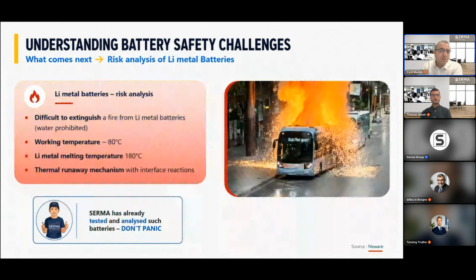The same also happens for the next generation. So here the lithium metal battery first. Here there is some fire. When it takes fire, you see that the fire is not exactly the same. Here it's not the electrolytes that burn. It's mostly, and you see some particles in this picture here, lithium metal that is melted. The disadvantage in the risk analysis is that this battery is working from 80 degrees and that the lithium metal is melting at 180 degrees.